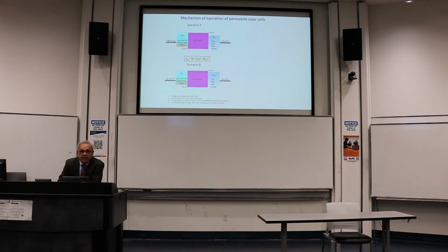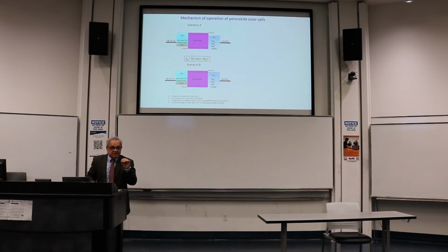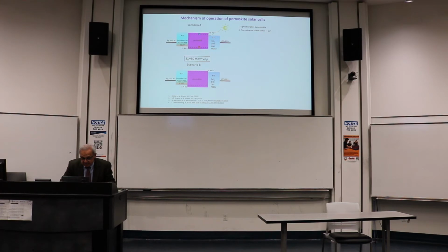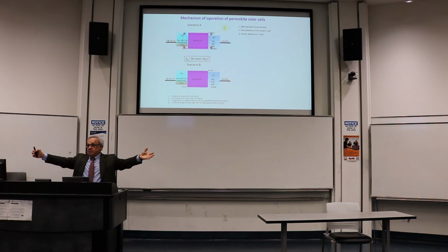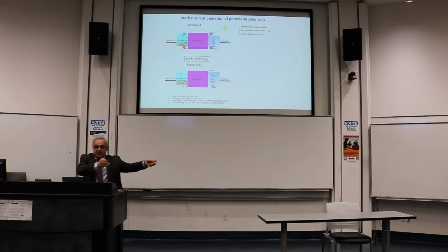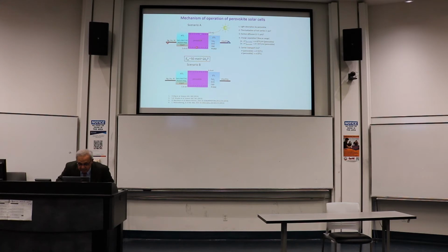Let me show you how it works. It works somehow similar to organic. Look, there are two scenarios. You create carriers, they create an exciton, and then this couple travels a long distance, not 20 nanometers like in organic. They go for microns. This is one unique property of perovskite. Nobody knows why it happens, but the carriers can travel long distance, not only carriers but also excitons. And then you separate them, and that creates the charges. The energy of the coupling is very small, around the energy of room temperature.